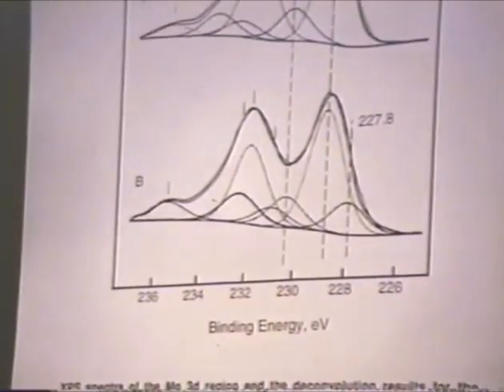Now we are looking at molybdenum 3d region of the XPS spectra and the deconvolution results. Well, we see the three molybdenum 3d peaks that are about 228.8, 230.4, and then a very small one around 232. These correspond to molybdenum nitride, Mo2N, and in really very small amount, possibly a molybdenum plus 6 species. Now, this is the catalyst which has been just activated.